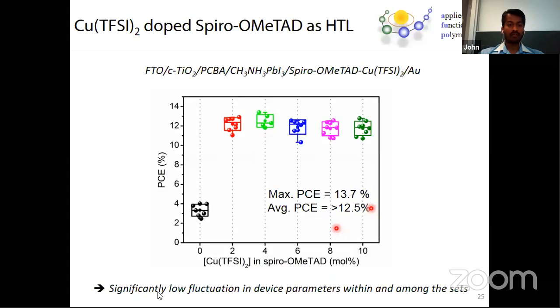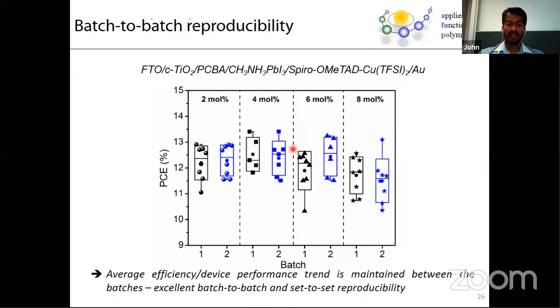So the point is, no matter that you are increasing the conductivity of your system with increasing dopant concentration, the device efficiency remains almost the same, or at least it is not disturbed by the increased dopant concentration in our case. And also you could see that device performance is not quite scattered throughout the system. We could obtain highly reliable, highly reproducible devices one after another in different batches. And here again, the batch to batch reproducibility of the system.